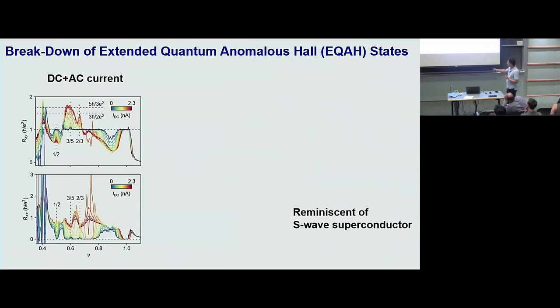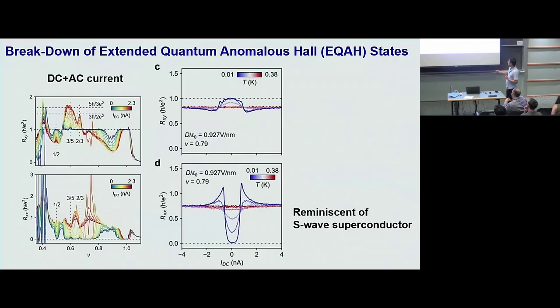So if you park here at a certain filling factor, for example 0.79, what you find is that at small DC current, you have Rxx almost vanishing, and Rxy is quantized at h/e². This is that fragile integer quantum anomalous Hall state.